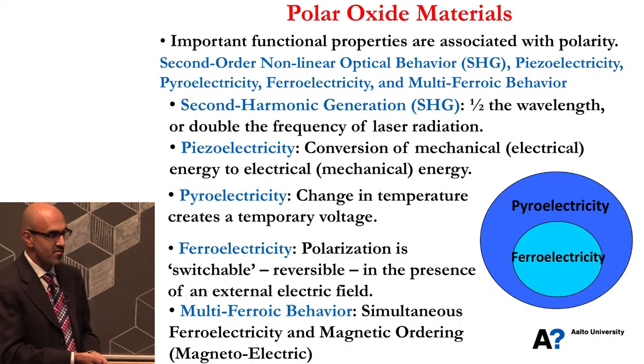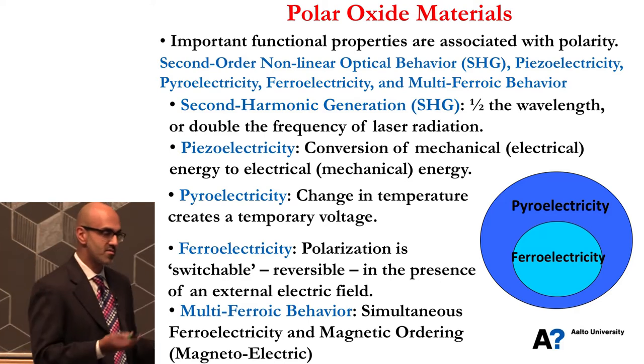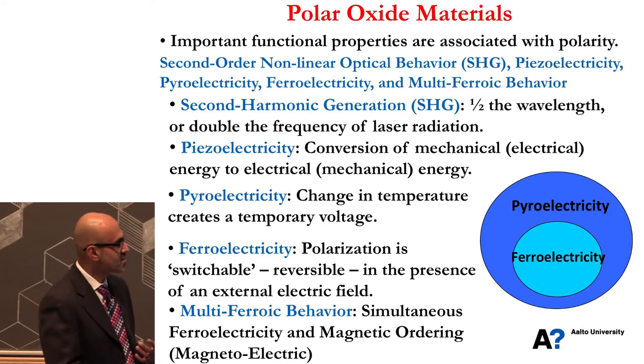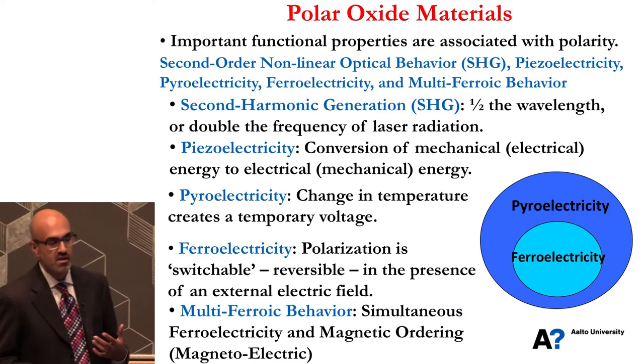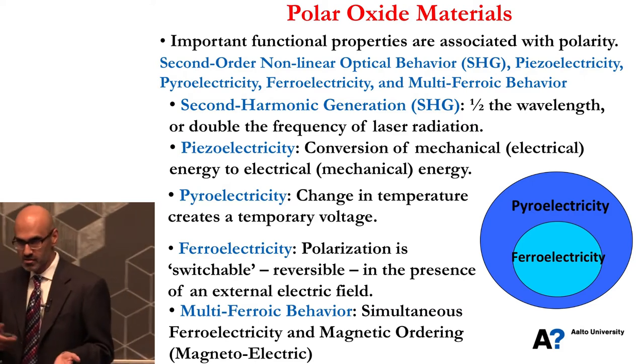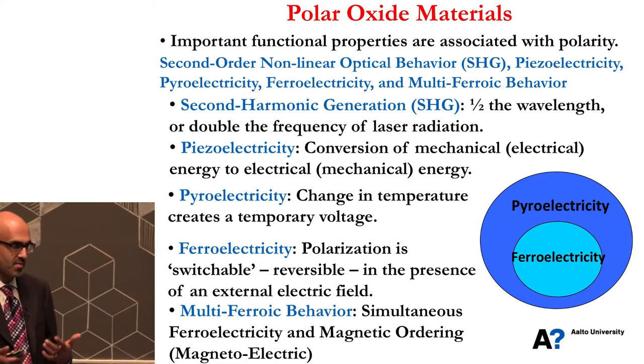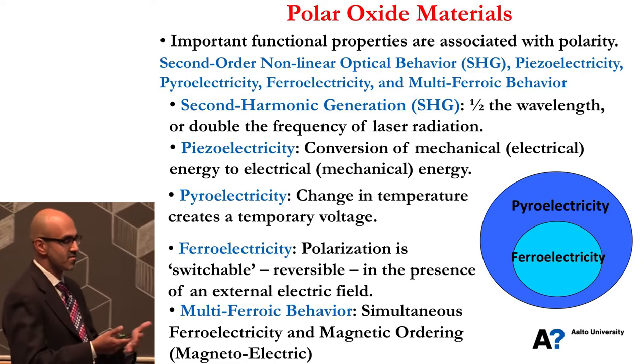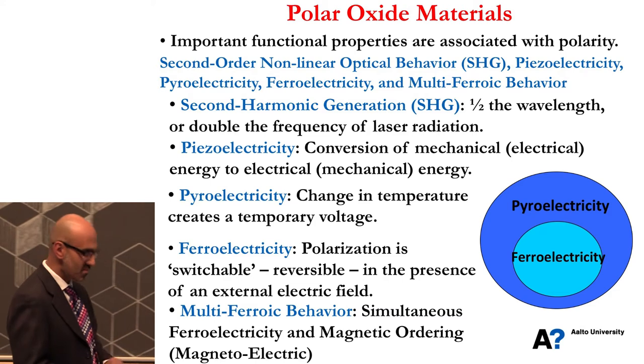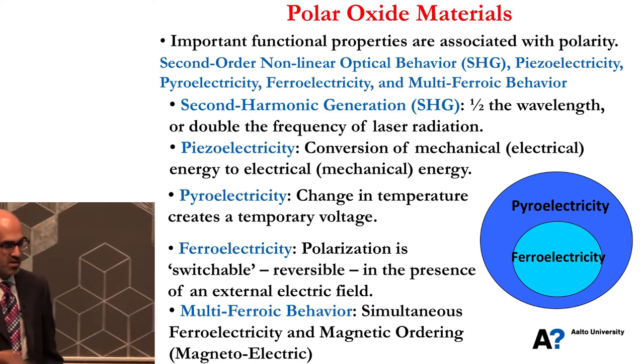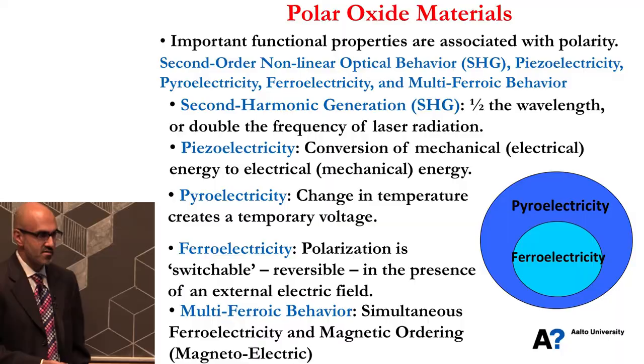These are materials that can do this, and they are all polar compounds. Finally, a ferroelectric — the polarization is reversible in the presence of an external electric field. Pyroelectrics and ferroelectrics are related: all ferroelectrics are pyroelectric, but the converse isn't true. In most cases pyroelectrics are not ferroelectric — the polarization is simply frozen. Multiferroic behavior involves some magnetism along with ferroelectricity.